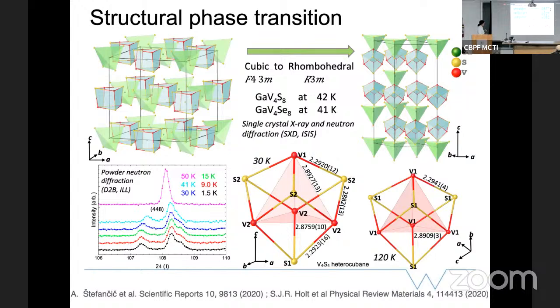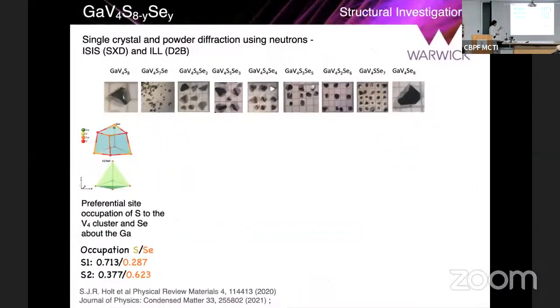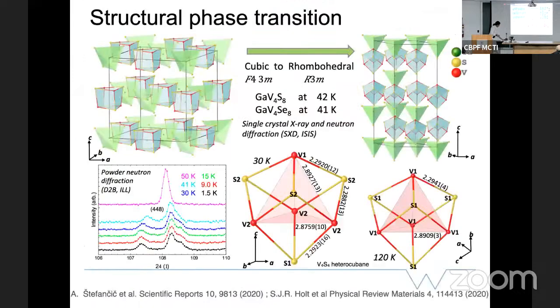So if you follow the powder diffraction as a function of temperature, you see that at 50 K, which is above the structural transition, if you follow the 448 peak, for example, it's a single peak. And if you go down in temperature, you find the splitting very, very clearly. So we can exactly pinpoint where the structural transition takes place, and also follow the distortions that happen between the structural units here. Okay. It's taking a while to register the transition. Thank you.